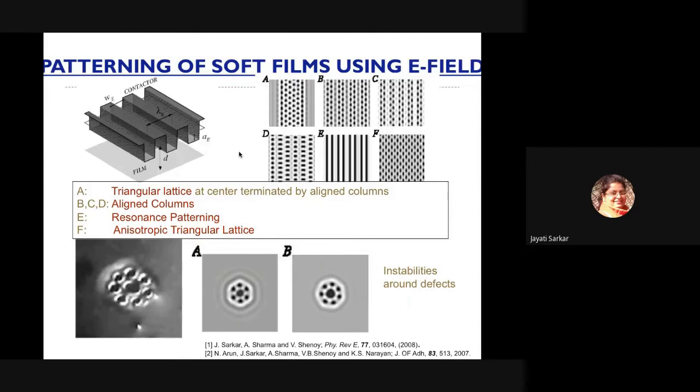With Van der Waals interaction, you can never control the strength, right? It always remains the same. Also you can see that the electric fields are rather long range than Van der Waals interaction. So the columns that you can form are much higher than those found in the case of Van der Waals interaction. So it can be totally controllable, right? But you cannot control the wavelength. That is actually found out from the energetics of the film. But you can control the voltage or the thickness or the amplitude or the aspect ratio of these patterns that are created.